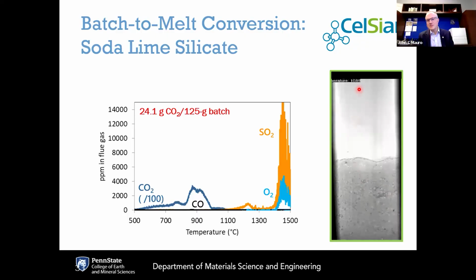And see, this is ramping up to 1100 degrees C, with faster and faster reaction kinetics. The plot on the left shows measurement of the gases being released during this process. You can see by far the most gas released is CO2. This is the CO2 concentration divided by 100. If you integrate this, you get 24.1 grams being released.